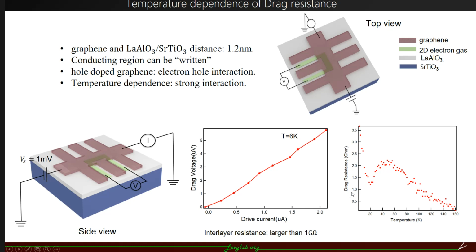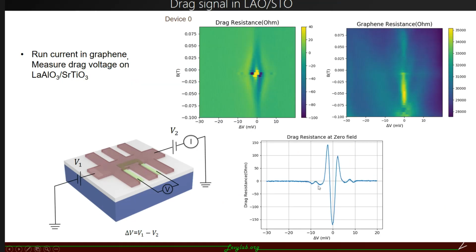And here is the temperature dependence of the drag resistance. We also measure the drag signal in the LAO/STO as a function of the magnetic field and the voltage applied on the graphene leads. Here we apply voltage on both ends of the graphene leads and then subtract the two to get a delta V. So we plot the drag resistance as a function of B and delta V. There are two main features of this LAO/STO drag signal. One is the superconductivity feature of LAO/STO.